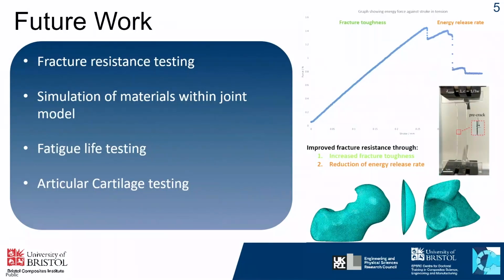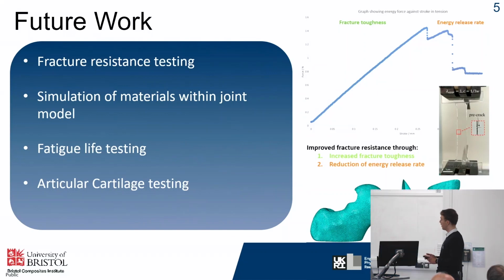In terms of the future work, I plan to carry out further fracture resistance testing and looking at how additives improve the fracture resistance. So this is a combination of the fracture toughness of the material, which is the point at which the crack propagates, and also the energy release rate, which is the rate at which the energy is released through crack propagation. More simulation testing, the fatigue life of the materials, so the materials must undergo many cycles of loading, and finally harvesting real human articular cartilage and running micro indentation testing on this to compare to my soft materials.